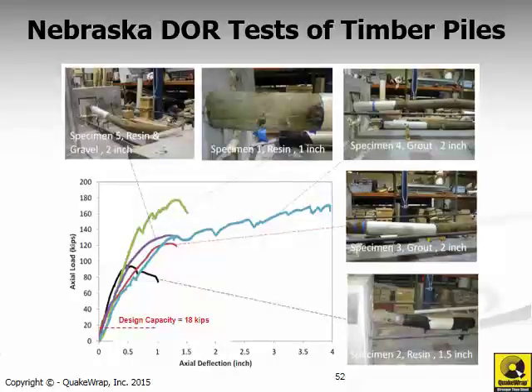Nebraska Department of Roads was interested in this PileMedic product and funded a study that was recently completed. In that study, they took 5 timber piles and shaved them into an hourglass shape, filled the voided area with some grout or gravel, wrapped it with PileMedic jackets, and injected resin to bond everything together. They retested these piles subjected to axial and lateral loads, and the results are summarized in this graph. As you can see, in all cases, the repaired columns, even though they were originally severely damaged, are significantly stronger than the design capacity of the original undamaged columns or piles.